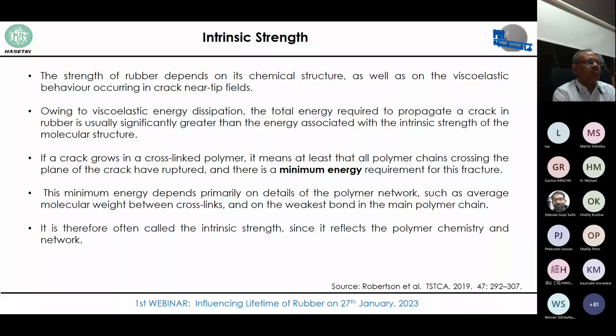And there is a minimum energy requirement for propagating this crack or cutting these polymer chains. And this minimum energy depends primarily on the details of the polymer network, such as average molecular weight between crosslinks and on the weakest bond in the main polymer chain. This was also explained in detail in the previous presentation, and it is therefore often called the intrinsic strength since it reflects the polymer chemistry and the network.